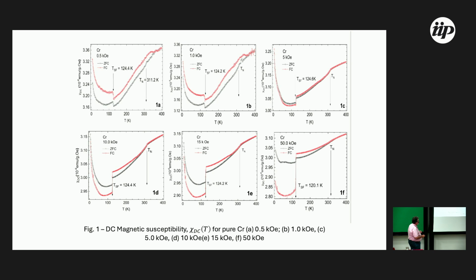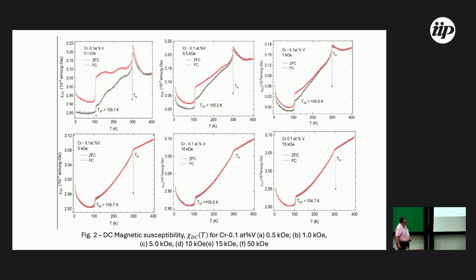This transition produces the big jump here. Okay? Compare the increase in zero field cooling and field cooling. These are chromium 0.1. Chromium 0.1 and the increase in temperature is a jump associated with local magnetic moment and the Curie-Weiss behavior.